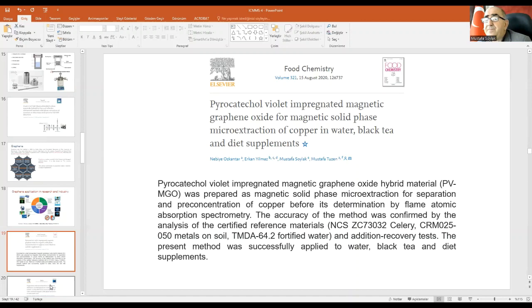After impregnation with a suitable ligand, here pyrocatechol violet, we could easily adsorb copper II on the surface of these materials. Then we applied this methodology for the solid phase extraction of copper from water samples.